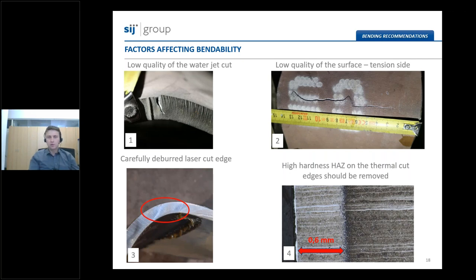And the last, so the fourth picture, presents the microstructure of SIMAXX 1000 grade, which was cut with the plasma cutter. This microstructure is something that we can only see in the laboratory during the microstructural observations. And even though this heat affected zone is really narrow, the hardness in this region can increase drastically due to the thermal input during the cutting process. So the hard microstructure is typically much more prone to cracking compared to the base material.